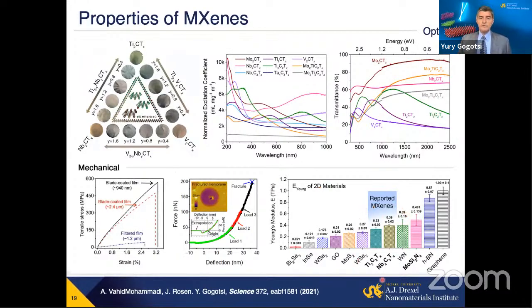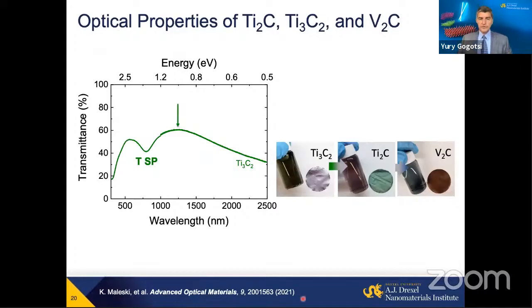And they're also very strong. They are the strongest of the solution processed materials. Ideal boron nitride or graphene separated from crystals, or a couple of CVD grown materials, may have higher mechanical strength, but they're strong, and they say reduced graphene oxide or graphene oxide here. So what is important? We need to look at this complex of properties to understand where the applications could be. And again, one of the key things here is that those properties are tunable.